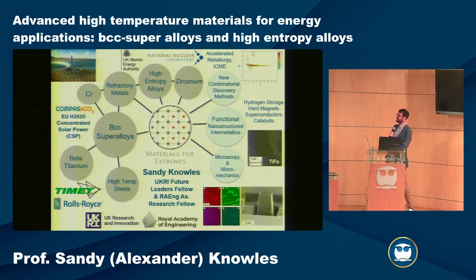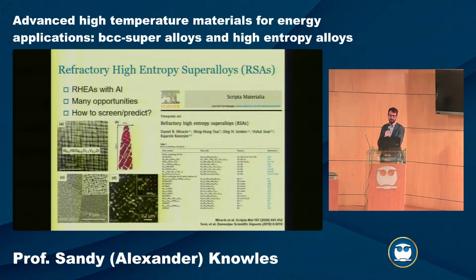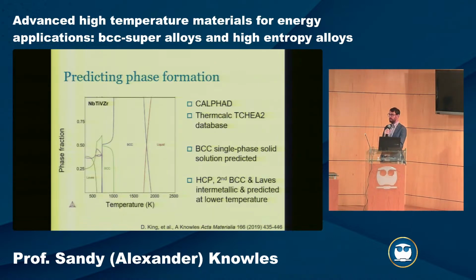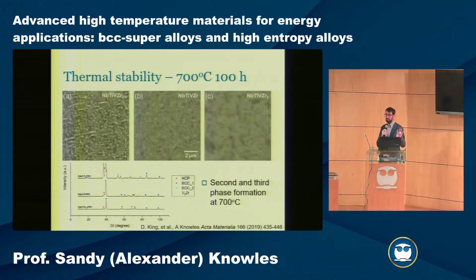The question is whether there is some limitation or problem, and whether it is possible to have cementite or some brittle phase in a high entropy alloy. Yeah, it's an interesting one. Say, for example, in the system we studied, we had predicted potentially some Laves phase and we do observe some of this Laves phase. It's a bit of a question around what is brittle. In this sense, when we did the work looking at the slip system type with Vincent's work, where we have these 100 versus 111 dislocation types, if you have the wrong intermetallic and you can't have a dislocation pass from the matrix into the second phase, you might have a brittle failure, because the dislocations will just accumulate, the load is created at the interface, and you then get a brittle failure.